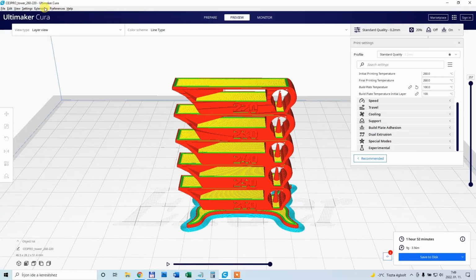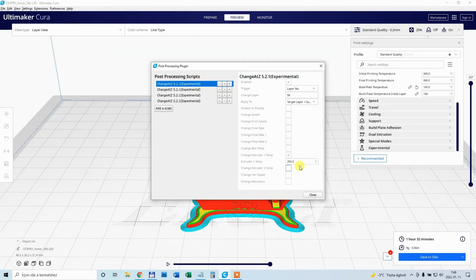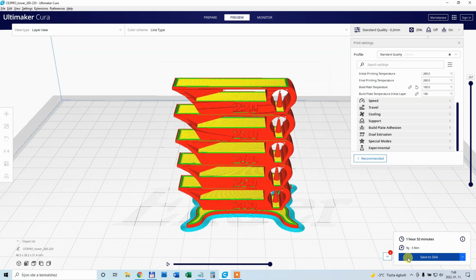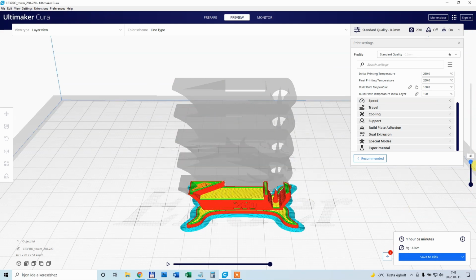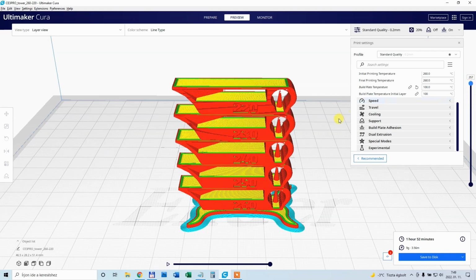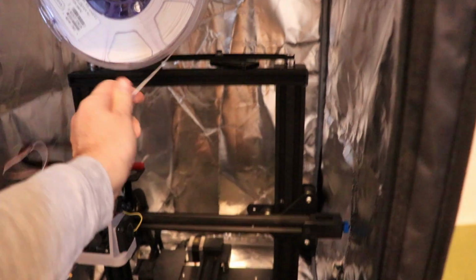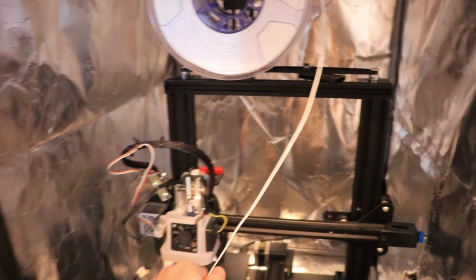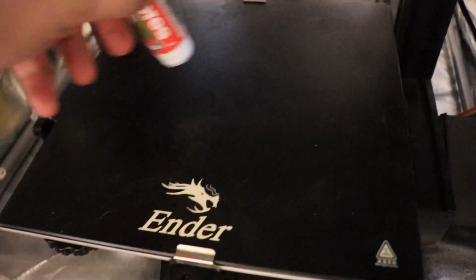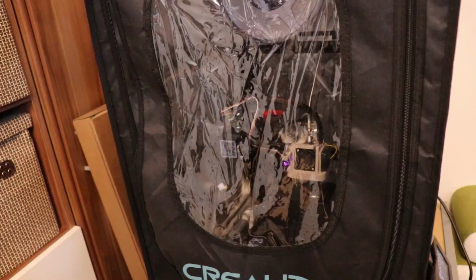I'm starting with a temperature tower, so I can decide at which temperature I will print. Here you can see the modifying of the G-code to change the temperature at a certain layer position. And this is the compact temperature tower by Izod from Thingiverse. As I mentioned earlier, I'm using a glue stick for better bed adhesion, and inside the enclosure will be approximately 45 degrees Celsius.